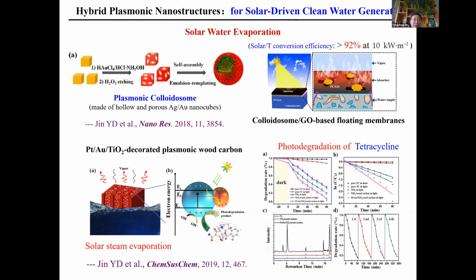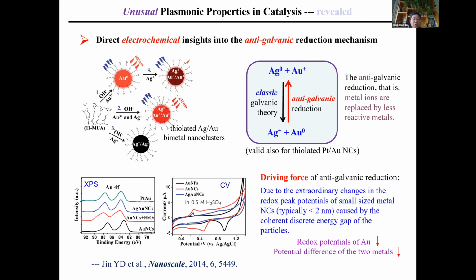We also, since plasmonic nanostructures have good photothermal conversion ability, prepared some plasmonic colloidosome and also platinum gold titanium dioxide decorated plasmonic wood carbon, and use them as floating membrane for high efficiency solar steam evaporation and also further degradation of tetracycline. Very importantly, during the experiment, we also revealed some unusual plasmonic properties. In the case of thiolated gold silver bimetal nanoclusters, we observed the anti-galvanic reduction phenomenon.